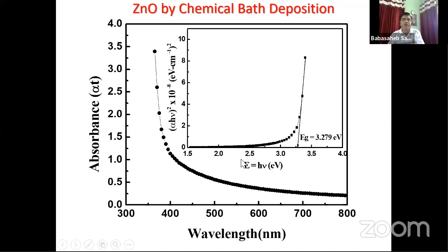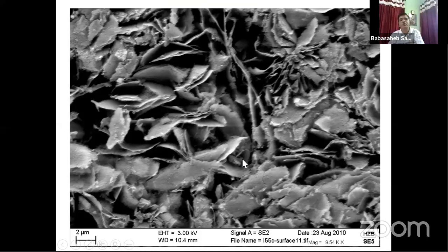But another criterion of this zinc oxide is that it should have a very high surface area. So we took some surface morphological images of this zinc oxide. Here you can see a 2 micrometer scale bar, and a petal-like morphology of the zinc oxide. But here it is not clearly visible whether this zinc oxide has a very high surface area or whether the interconnection of the nanoparticles is there or not.